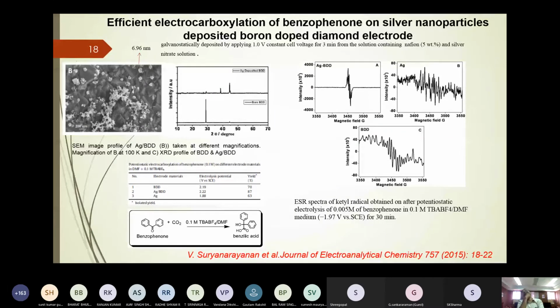This shows that silver BDD is superior to other electrodes for the conversion of benzophenone to benzilic acid. Why does it show higher yield? We can confirm by ESR spectroscopy. All we know about ESR, electron spin resonance. Here the important thing is, as I showed earlier, how the mechanism goes: benzophenone forms a ketyl radical, which abstracts carbon dioxide followed by a single electron transfer to form the product. Here if we have more ketyl radical, we get more product.